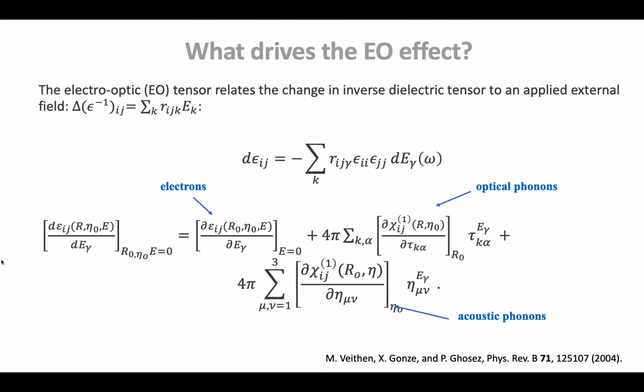But you also move your ions, and we know that susceptibility normally is computed for the equilibrium position of ions. If you apply force by electric field, they are shifted, so you can expand in Taylor series. This is the first derivative of chi, and so that's called Raman susceptibility. That's a Raman effect. And this is optical phonons.